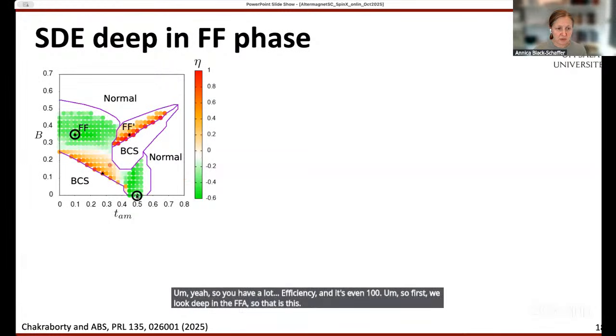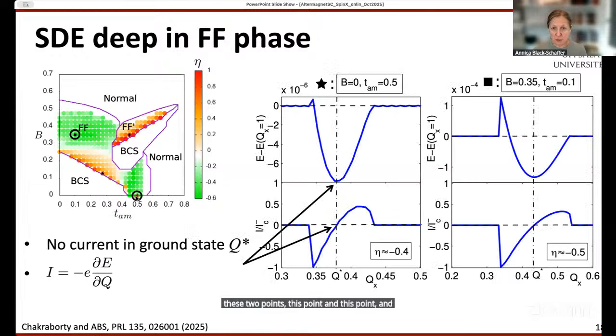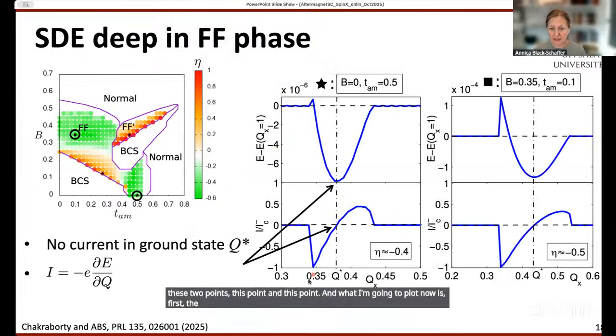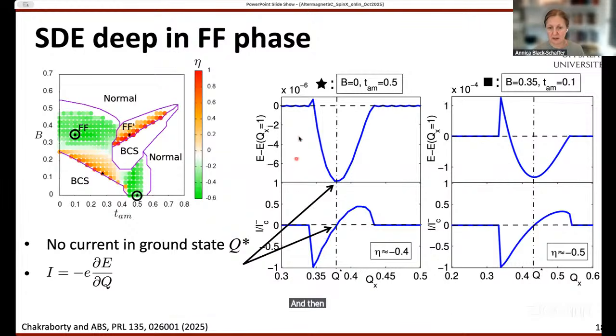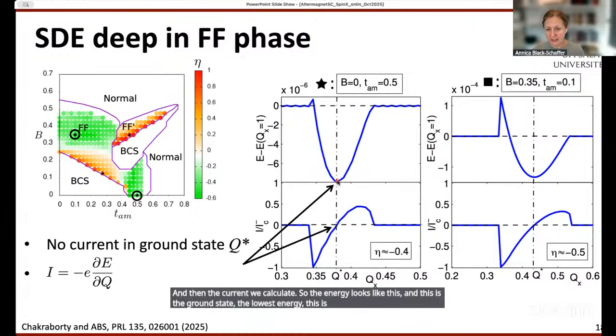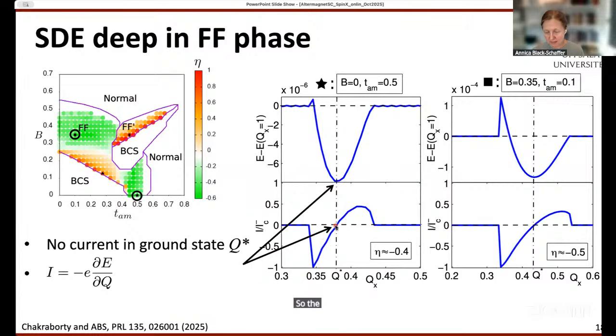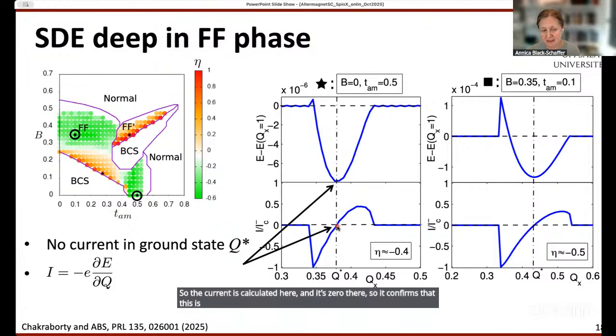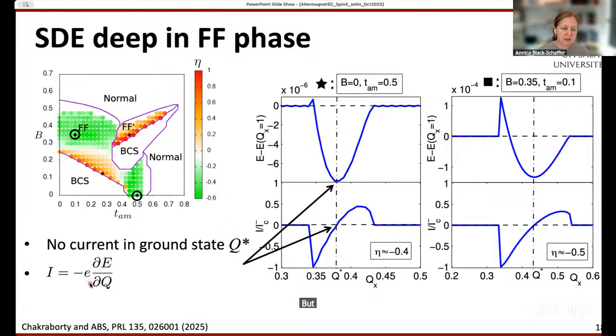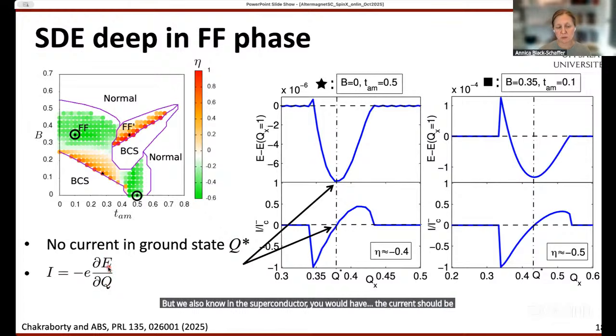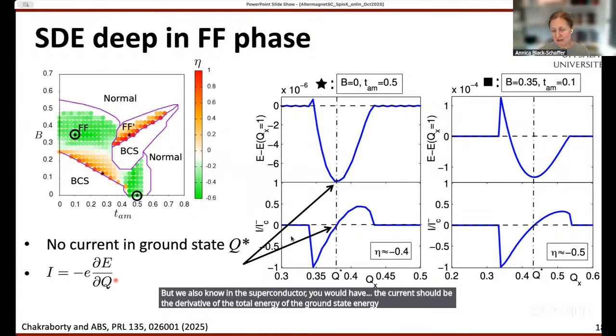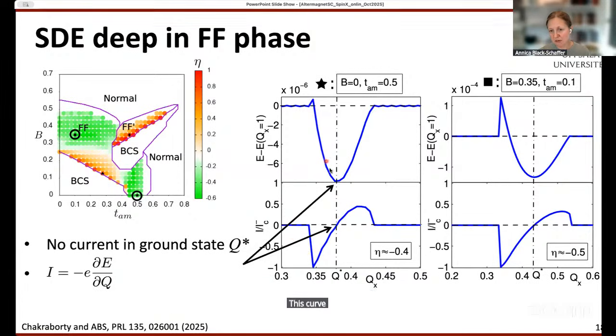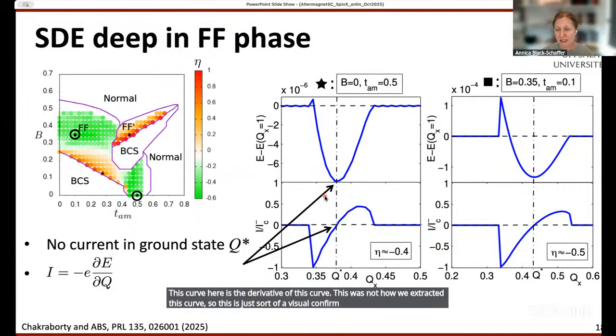First we look deep in the FFA, so that is these two points, this point and this point. What I'm going to plot now is first the energy landscape as a function of Q, and then the current we calculate. So the energy looks like this, and this is the ground state, the lowest energy, this is Q star. And then we calculate the current. The current is calculated here, and it's 0 there, so it confirms that this is indeed the ground state. But we also know that in a superconductor, the current should be the derivative of the total ground state energy as a function of Q. And we do see that here, that this curve is the derivative of this curve. This was not how we extracted this curve, so this is just a visual confirmation that what we're doing is correct.